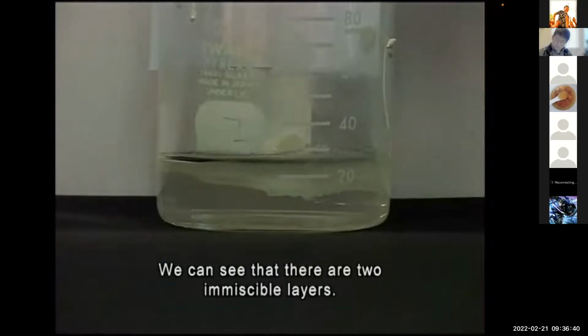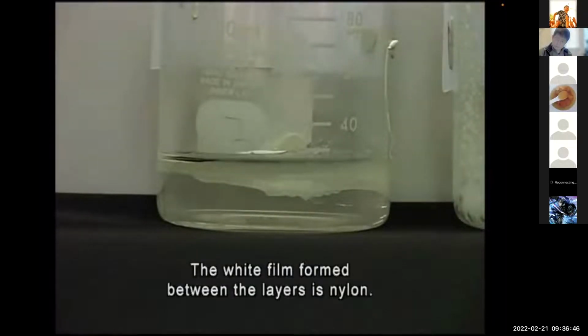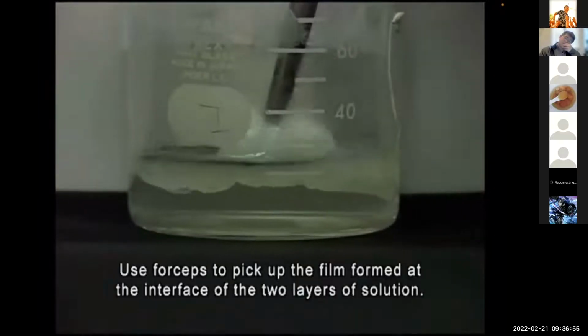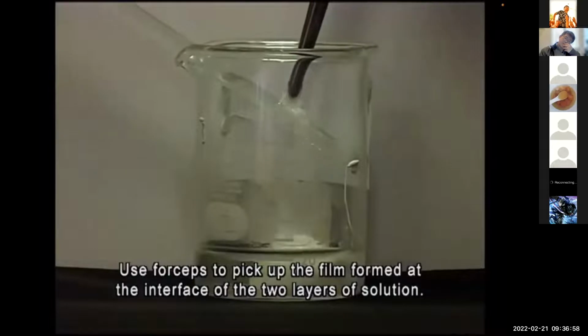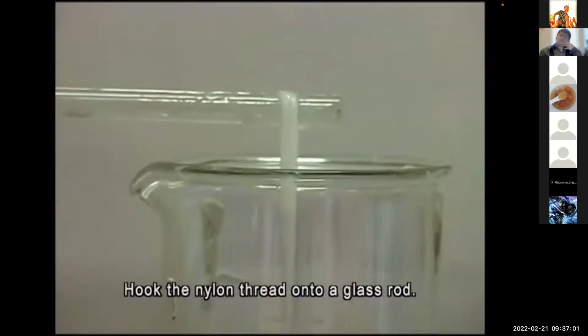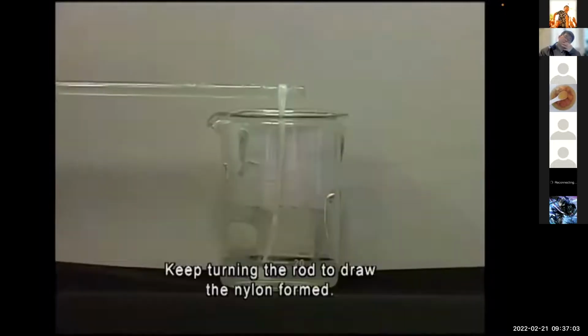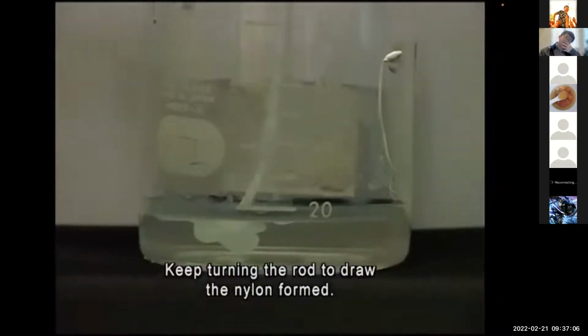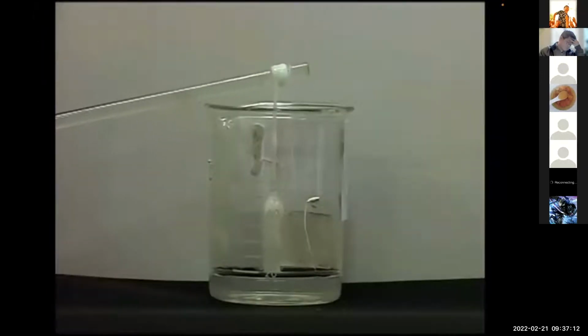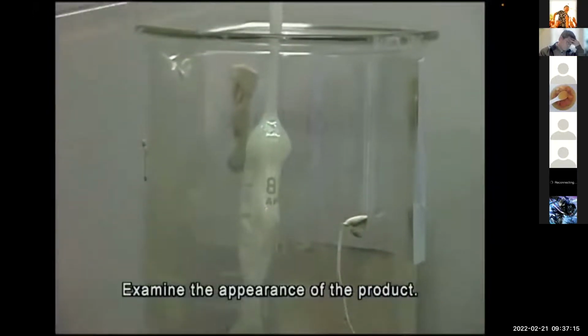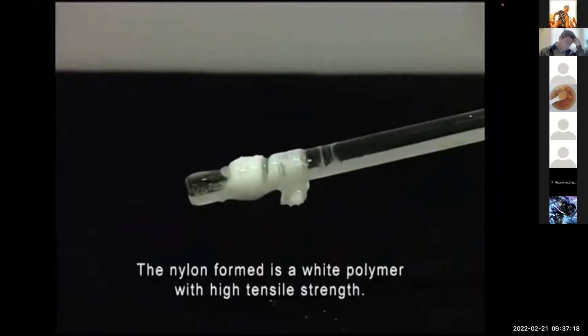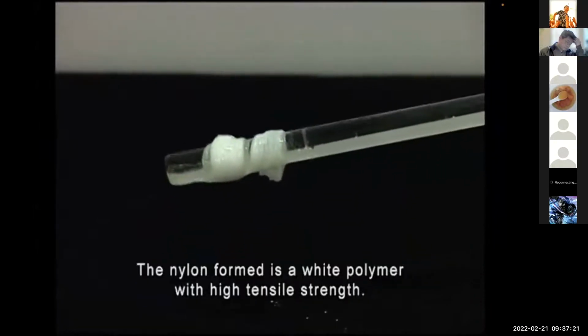We can see that there are two immiscible layers. The white film formed between the layers is nylon. Use forceps to pick up the film formed at the interface of the two layers of solution. Hook the nylon thread onto a glass rod. Keep turning the rod to draw the nylon formed. Examine the appearance of the product. The nylon formed is a white polymer with high tensile strength.